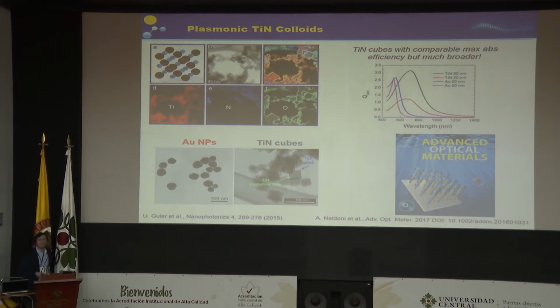What we were interested in doing was to compare the potential of titanium nitride versus gold particles, which is usually the benchmark material for this kind of study. And as we can see here from the cross-section of absorption, titanium nitride presents really different properties with respect to gold. We can see that gold presents a sharp resonance in the visible. Otherwise, for titanium nitride with similar particles, like this nanocube with the same dimension, we have a much broader absorption cross-section, so we can cover a much bigger wavelength range. And so, of course, we can absorb much more light and use it for our purpose, in this case, water splitting.